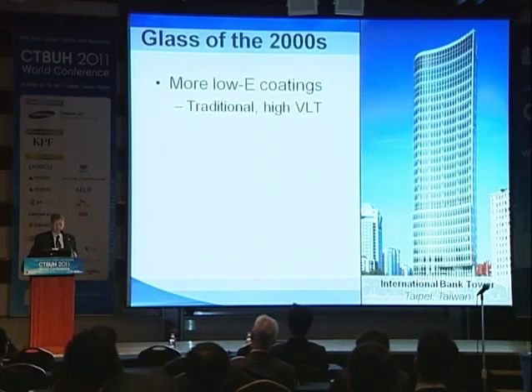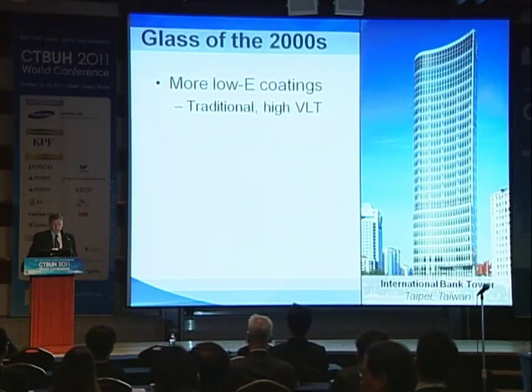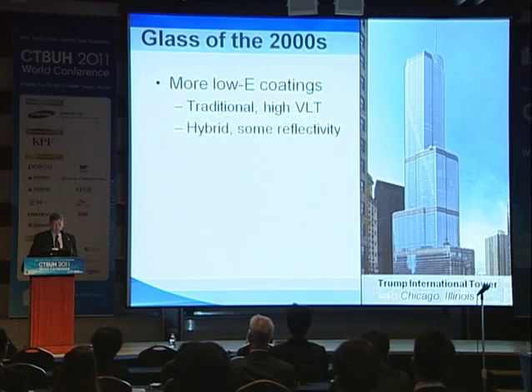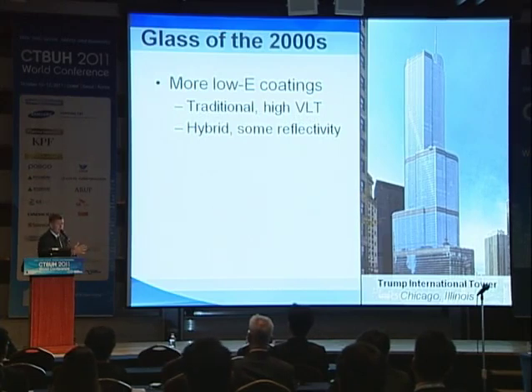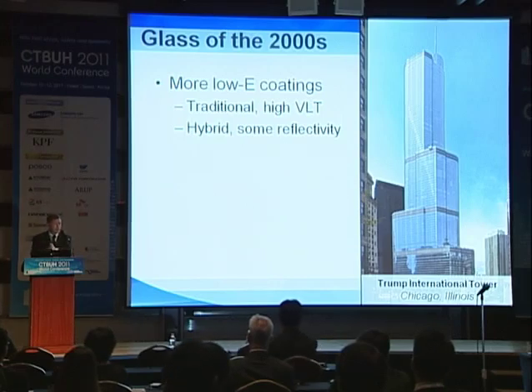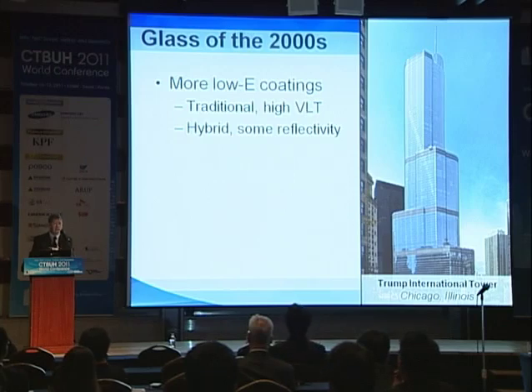As we moved into the 2000s, we saw more low-E coatings being used with higher visible light transmissions. We also started seeing hybrid coatings come into play. When I'm talking about hybrid coatings, essentially what they were was to take a high-performance reflective coating, the best attributes of that, and blend that with the best attributes of a low emissivity coating. So essentially what you had was a high-performance product that gave you fairly high light transmission, had some degree of reflectivity to it, but gave you excellent solar performance characteristics.